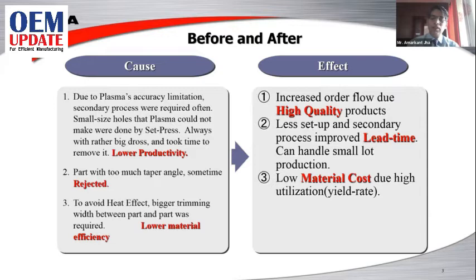Also, plasma has a characteristic of taper cut. The edges are tapered. So many times the products were rejected. The Japanese quality, how much they believe. So many times their jobs were rejected because of the taper angle. Also, the heat affected zone in plasma was much bigger than the laser. And because of this, the bridge material between the two parts is very high when you compare with the laser.